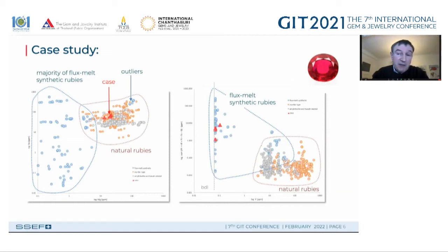And what you can see here in these two plots, we have on the left side gallium versus magnesium, and both axes are logarithmic scale. We see actually that this case is plotting in a field where the natural stones are found, together with some outliers of synthetic flux melt stones. But when we add the second plot, where we have vanadium versus elements which are normally coming from the crucible or from the flux melt itself, like rhodium, platinum, lead, and bismuth, then we clearly can identify such a stone as a synthetic stone.